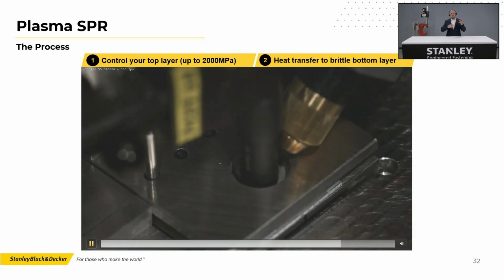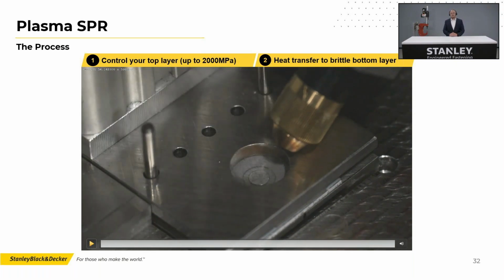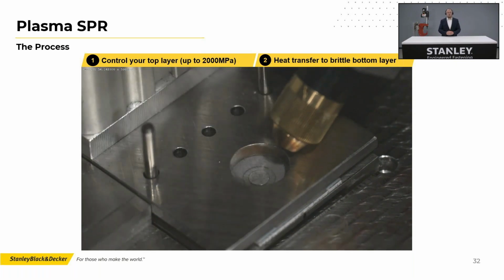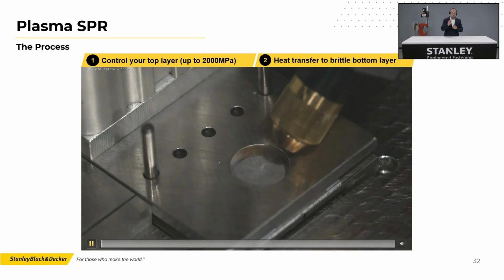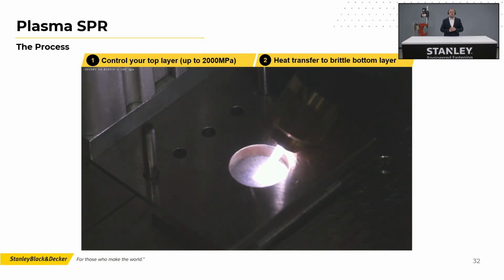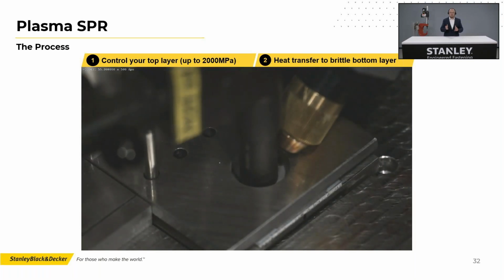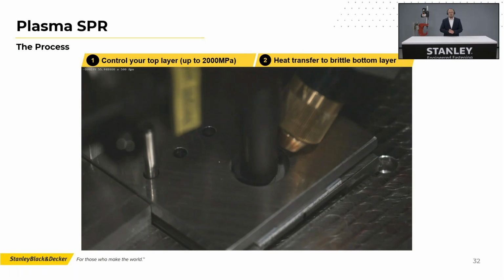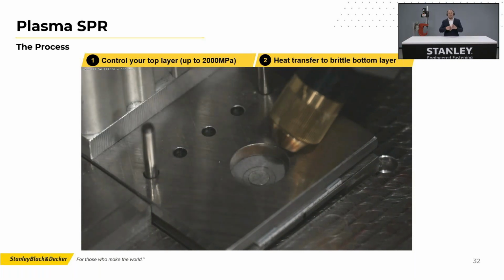You can see that the process overlaps a little bit and that it's quite fast. Okay, this is slow motion, but it's really quite fast. So we use the plasma, which is, by the way, around 2 centimeters away from the top metal sheet, to make the Usibor soft. We don't want it liquid. We just want it orange glowing to make it soft. Then we pierce through the Usibor with a rivet. And of course, why I want to talk about this in our castings webinar is that we also supply some heat to the bottom layer because the heat is traveling through the stack.